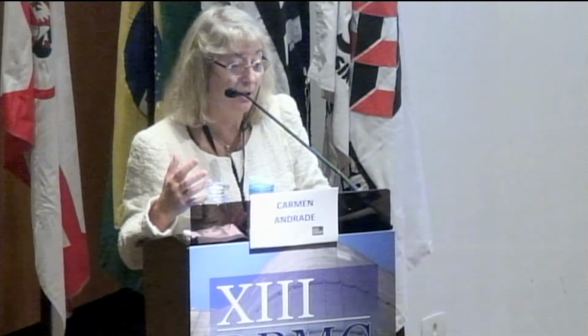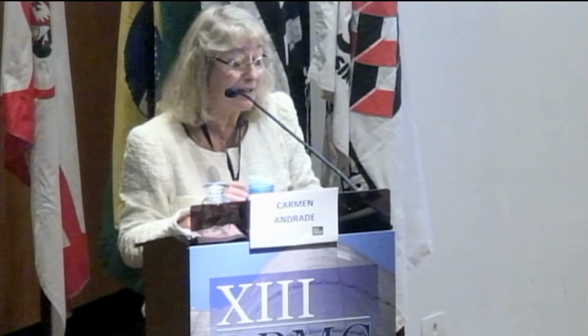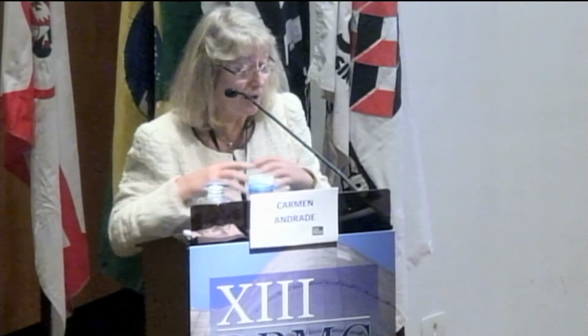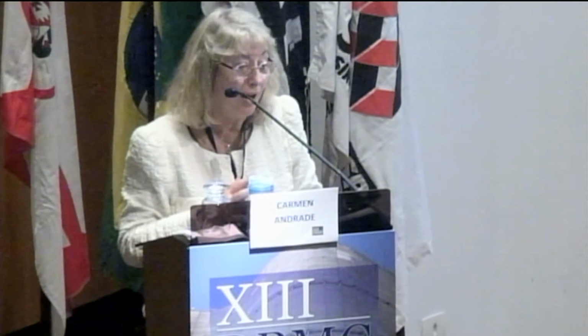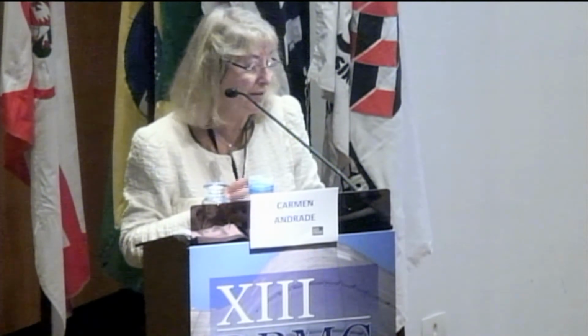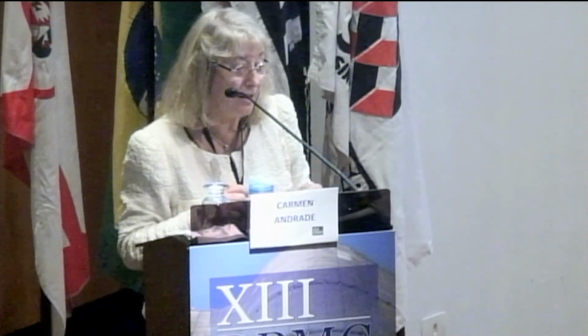Because we had the worst condition, there is more carbonation and high corrosion. We found corrosion rates of 3 and 5 microamperes, 30 and 50 micrometers per year, which are very high. This is important, as you say, on all the coast, but in my opinion it is well known. We know the rates of corrosion with the degree of saturation. We know them more or less with an accelerated test. If you are using OPC, you can use it. If you are using blended materials, you cannot use accelerated methods.